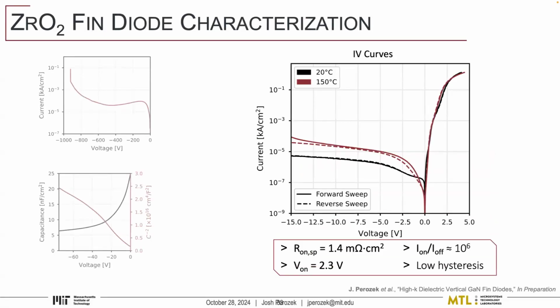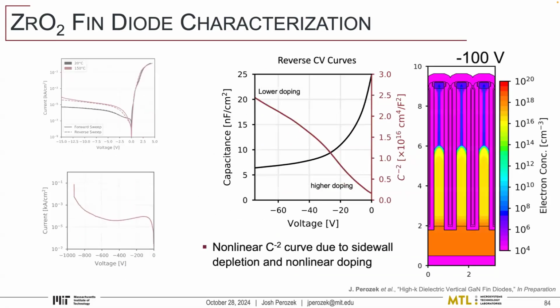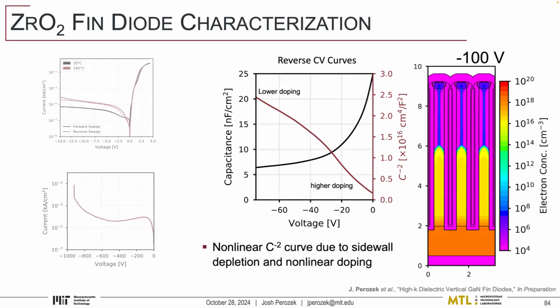diode. We have greater than 10^6 on-off ratio. There's low hysteresis. The specific on-resistance is about 1.4 milliohm square centimeter, which we'll benchmark in a little bit. So they work as diodes. The CV curves become a little more interesting. You'd normally expect for a Schottky diode for this red curve, the 1/C² term, to be linear. Because our doping profile is nonlinear, you see that effect come up in the capacitance there.